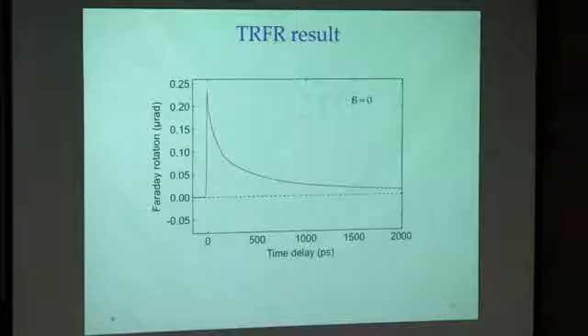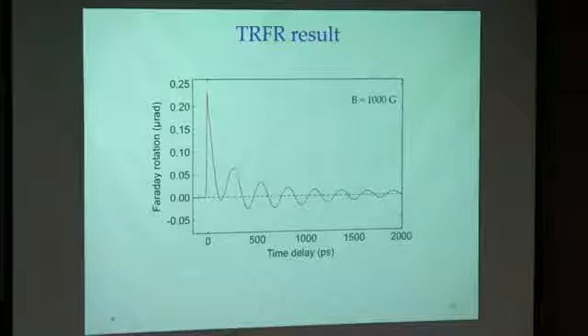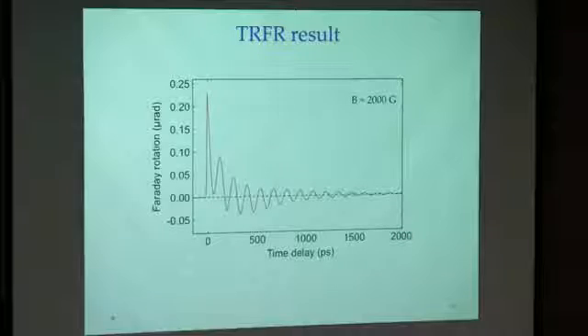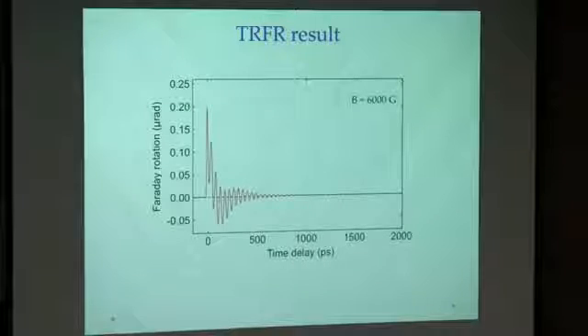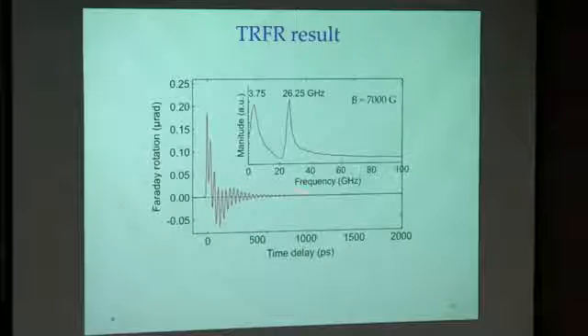Here's our result. This is the data at 0 magnetic field. Then we increase the magnetic field in the transverse direction, and we start seeing oscillations. So notice that the fields are thousands of Gauss. And we see oscillations. You probably noticed 2 frequencies already. And those 2 frequencies can be seen very well in the Fourier transform.